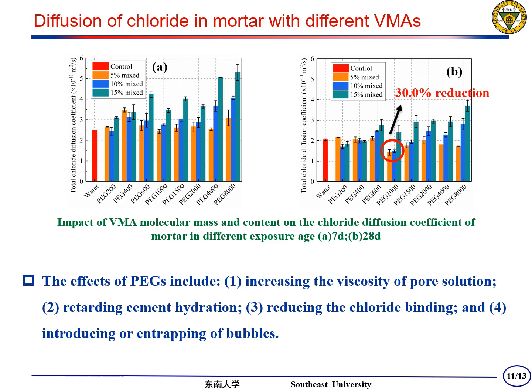For this unusual phenomenon, we believe that the effects of PEGs include increasing the viscosity of pore solution, retarding cement hydration, reducing the chloride binding, and introducing or entrapping of bubbles. At 7 days of exposure, the second and third effects dominate the diffusion of the samples with the presence of PEGs, and at 28 days of exposure, the first effect dominates the diffusion, due to the chloride binding achieves equilibrium.